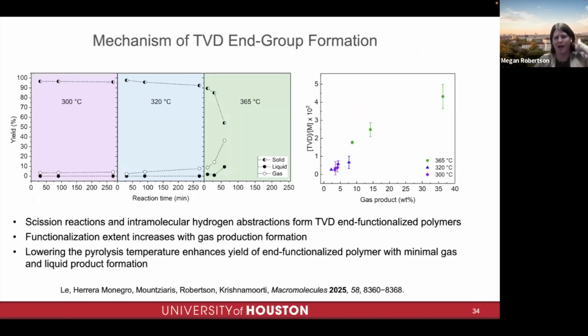Okay, so I'll just show you a little bit on this. Traditional polyolefin pyrolysis would be at temperatures of around 400, say. If we're in the 300 range, what we find, here's 365, there we're still forming a lot of liquid and gas. The solid content is maybe only 50%.